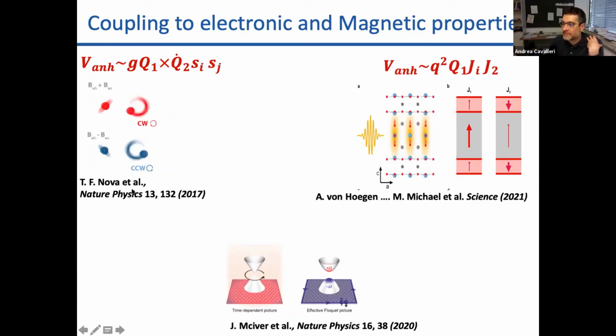There's again work by my student Tobia Nova, who's the same that did the work in the ferroelectric, who took excited phonons in certain ways in which phonons could be driven now in circles by combining pairs of excitations that would go in quadrature with one another between two phonons that are quasi-degenerate. What he showed was that he could exploit an anharmonic term of the type Q1 cross Q dot 2. So this is something that basically has to do with the angular momentum of these atoms that now are undergoing a very strange motion that they would normally not undergo. And he has used this to align and to drive spin excitations in a magnetic material.